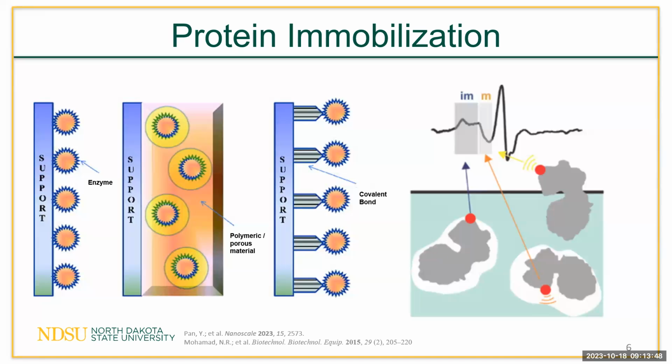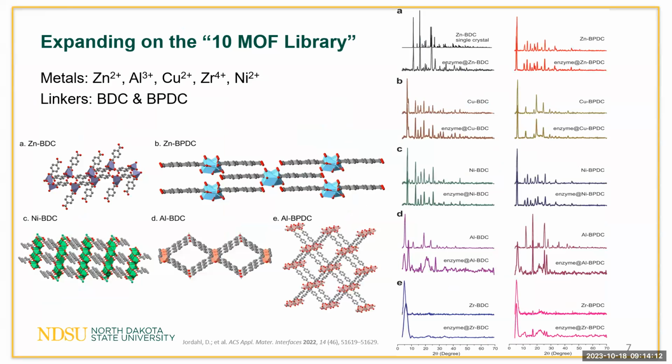Whereas if the protein is buried deep within the MOF, there may or may not be mobility depending on if the confinement is very packed and there's not a lot of room for the MTSL spin label to move, or if it's completely immobilized. So this is where we've started our EPR studies and analyzing these metal organic frameworks.